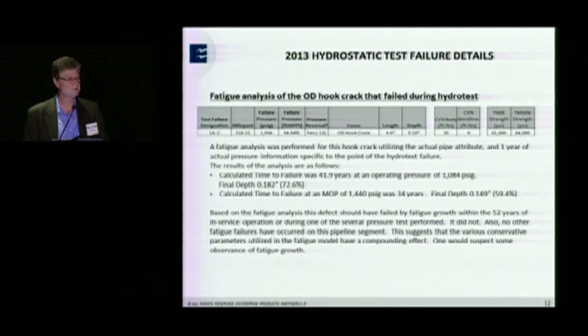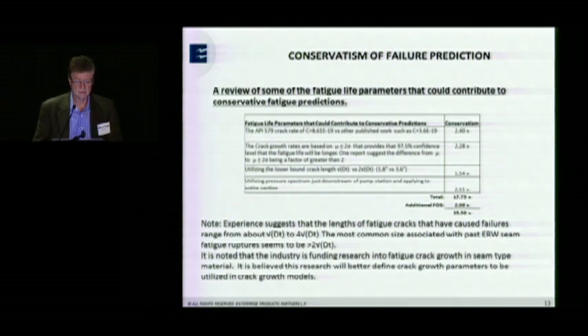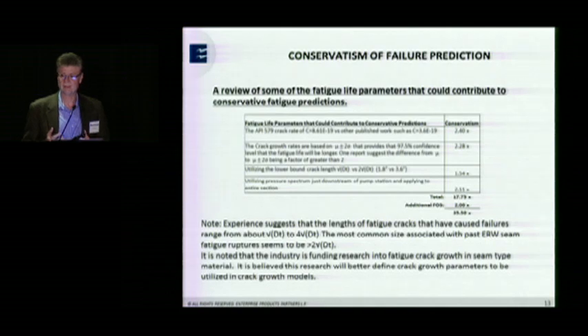And this is where I think we have to be careful sometimes when we do these analyses. I want to step back and point out there's some research going on looking at the constants in the Paris equations, specifically for ERW welds. But some of the potential conservatism in that is that Enterprise has been using the API 579 crack growth rate. As you can see here, it's 8.61 times 10 to the minus 19. There are others out there that can be used. Another one we've seen published is 3.6 times 10 to the minus 19. So the difference between those two models is a factor of safety of 2.4. If you use the other model, you would get 2.4 times longer life.